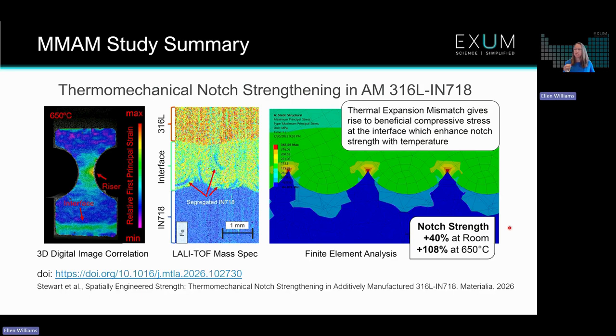You can see that the researchers did successfully create significantly stronger tensile bars by doing this multi-material additive manufacturing process. They showed 40% greater strength when doing tests at room temperature and over 100% greater strength at elevated temperature. And what you can see over here with the 3D digital image correlation coloring the first principal strain, this image was collected while the tensile test was occurring, is that even though there was compressive stress occurring at that interface, because of the thermal expansion mismatch, it actually kept that interface intact and allowed the notch to be the weak point. And so essentially these tensile bars did fail where they were intended to fail.